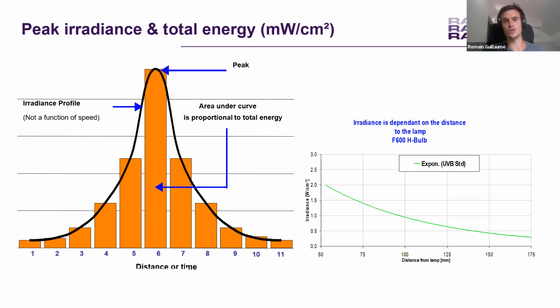When we take the area under this curve, we can have a good idea of the total energy that will be provided by our UV sources, taking into consideration the speed of the line also. And this irradiance profile is highly linked to the geometry of the lamp, and also to the distance between the lamp and your coating. On the drawing on the right, you have a curve representing the peak irradiance in watt per square centimeter on the vertical axis, decreasing as we increase the distance between the lamp and the coating.